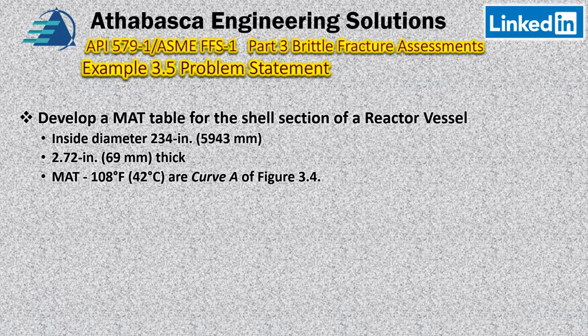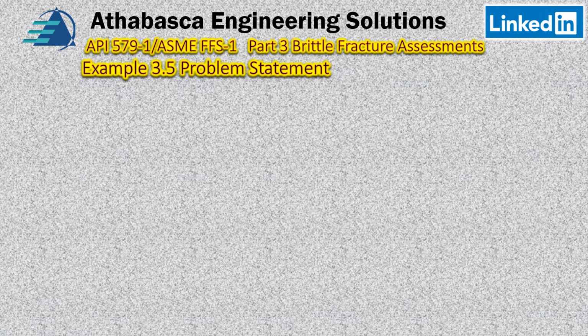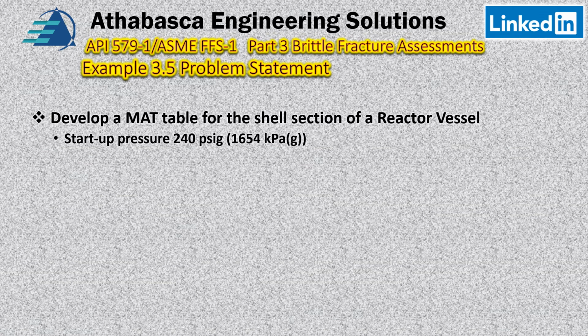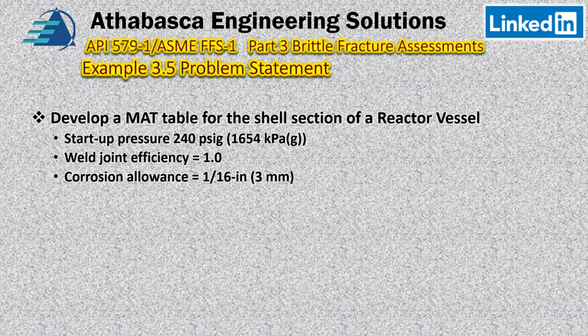The MAT is minus 108 degrees Fahrenheit or minus 42 centigrade, and we are in curve A of Figure 3.4. Now, if you want to learn how to do that, there are earlier episodes where we go through this in extreme detail. Start-up pressure is 240 PSIG or 1654 kPa. We have a weld efficiency of 1.0. We have a corrosion allowance of 1/16 of an inch, which is 3 millimeters. We have no impact test data available.